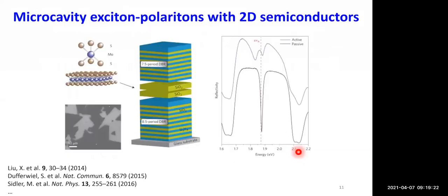So now, with that in mind, 2D materials provide a very good platform to realize these polaritonic phenomena, especially at room temperature, because they are mostly a disorder-free system, and you can grow them quite easily with CVD growth techniques that are relatively inexpensive, and you can also grow them on a wide variety of substrates. So microcavity polaritons in 2D materials were first demonstrated by Vinod Menon's group. And following this work, if we go back a few years, the focus had been mostly on neutral exciton complexes, with only very few efforts on other higher order charged exciton complexes in these microcavity systems. So in the first part of today's talk, I will present the strong light matter interaction of exciton, trion, and cavity photon in a microcavity system.